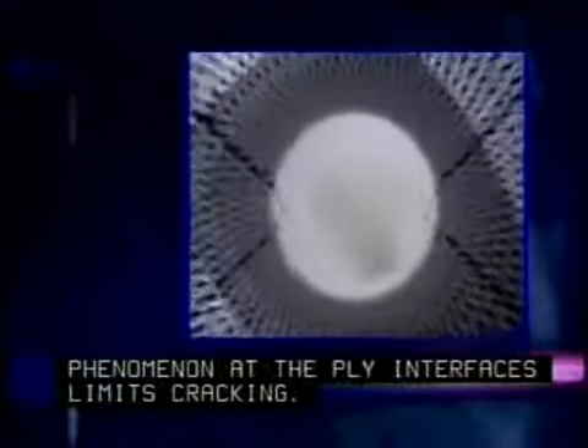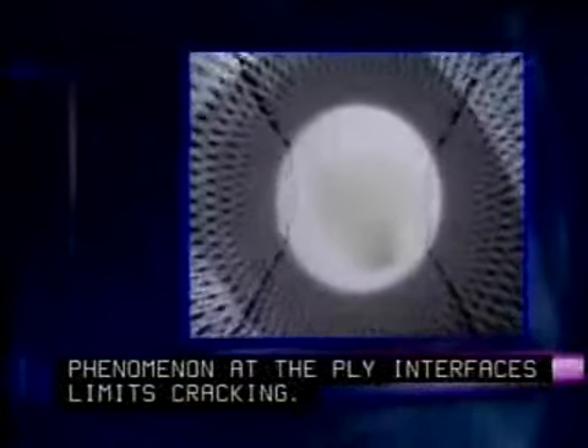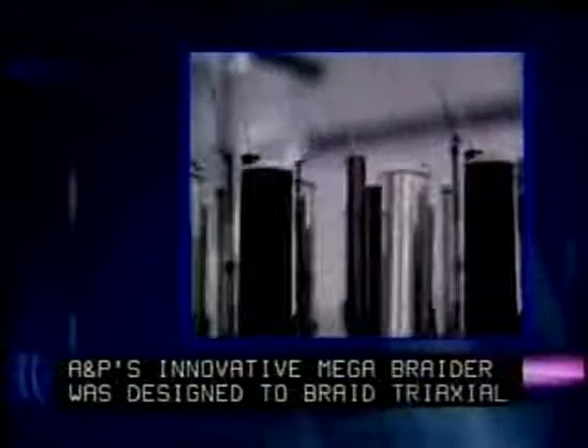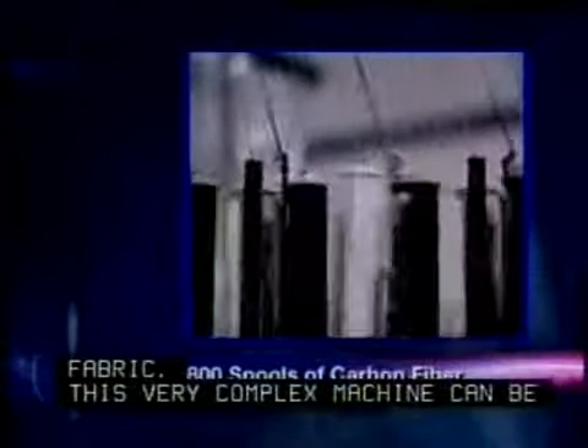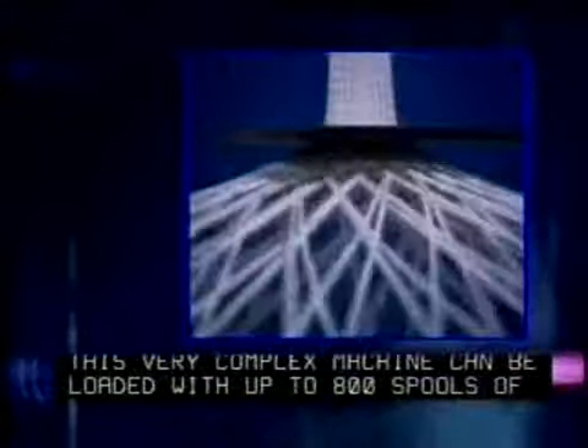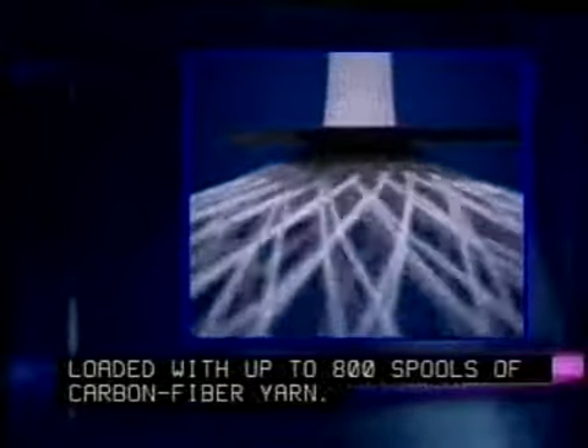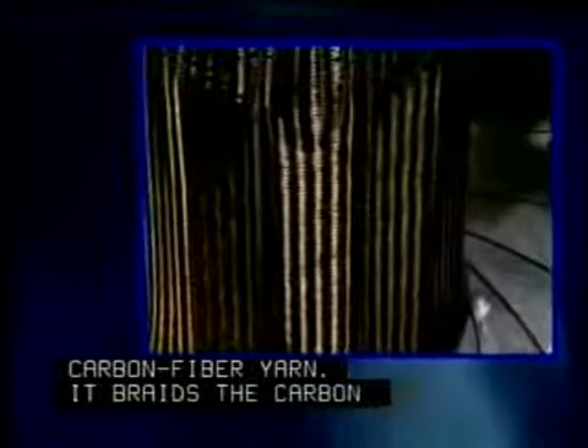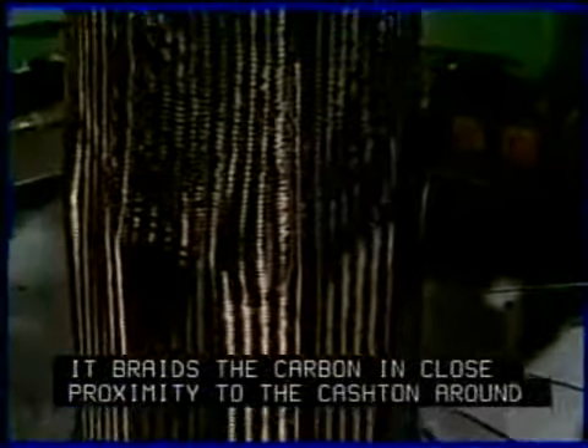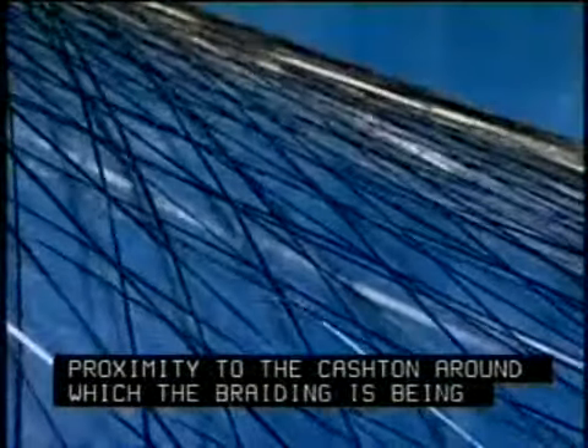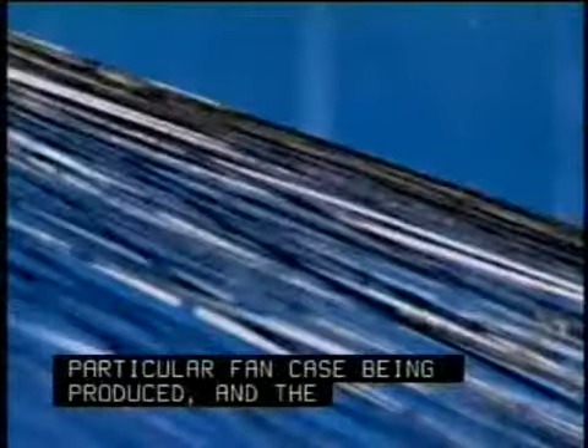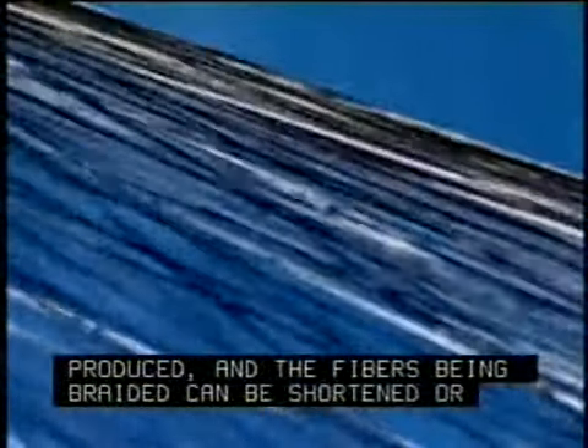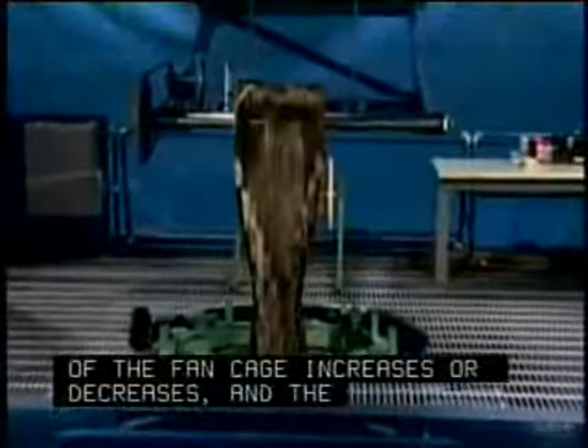A&P's innovative Mega Braider was designed to braid triaxial fabric. This very complex machine can be loaded with up to 800 spools of carbon fiber yarn. It braids the carbon in close proximity to the capstan around which the braiding is being wound. The capstan has the exact profile of the particular fan case being produced, and the fibers being braided can be shortened or lengthened as the circumference of the fan case increases or decreases, and the thickness of the plies can be increased where greater load tolerances are needed.